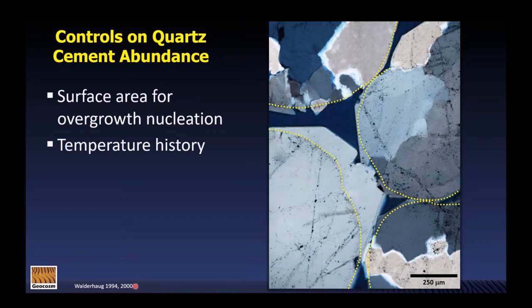Now, prior to his work, what people focused on primarily in trying to understand the spatial distribution of quartz was either the supply problem or the transport problem. The supply problem would be trying to track down where that dissolved silica, which grows as overgrowth, like this one over here, came from. There are a number of potential sources, of course, things like smectite illitization, albitization of plagioclase or K-feldspar, mainly plagioclase, and dissolution of quartz grains at stress contacts, for instance.